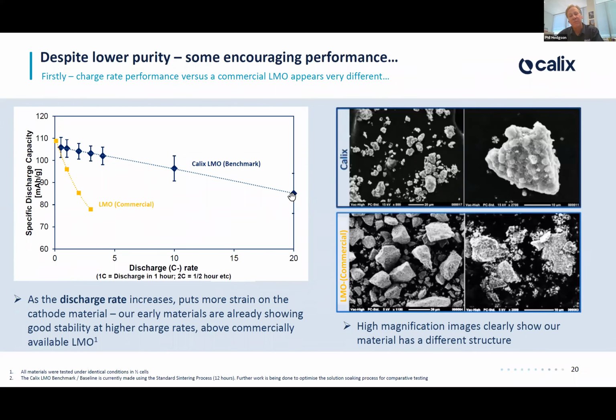We can take it up to very high discharge rates without a substantial loss in our capacity. So at 20 C discharge rate, we're discharging this material in 3 minutes. So it's a very, very fast discharge rate. And typically, most manganese structures do not handle that. That's why this commercial material hasn't even been tested beyond. So first of all, less pure, but performing very well.